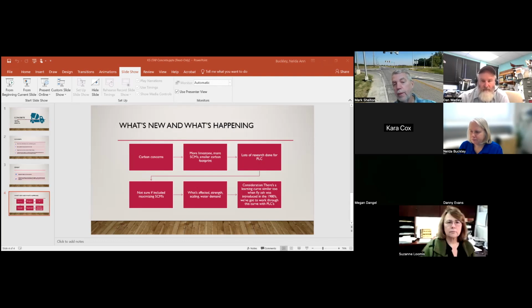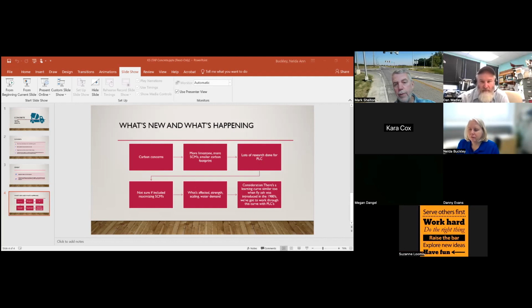There was lots of research that was done with the Portland limestone cements, looking at the different characteristics of the cement and the different values, and that's where they honed in on the right amount of limestone that should be added. What we're finding in some of the research and documents that come out today is that questions are arising. Was the research done using Portland limestone cement compared to Portland cement, but did it include these additions of the supplemental cementitious materials, and certainly at the higher amounts? Because what gets affected when you add these supplementary cementitious materials and the additional limestone is strength, and the rate of strength gain.